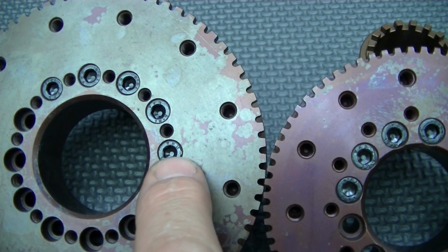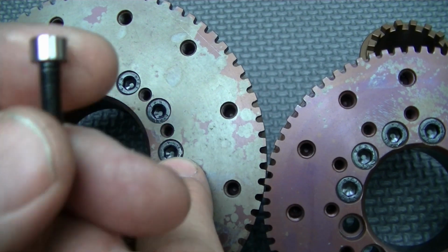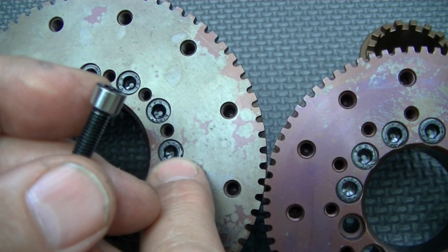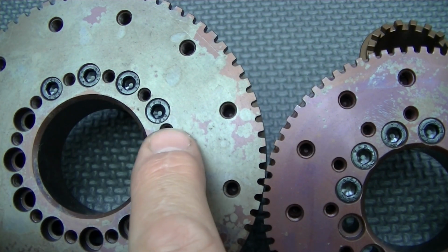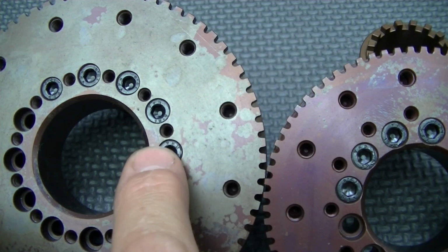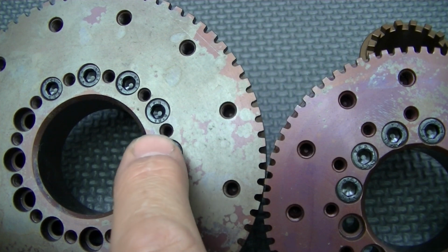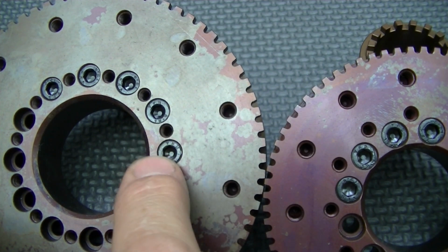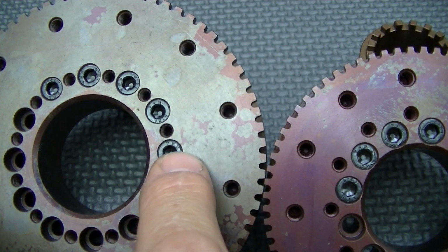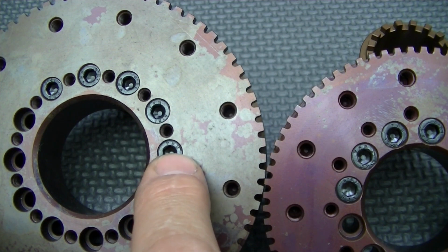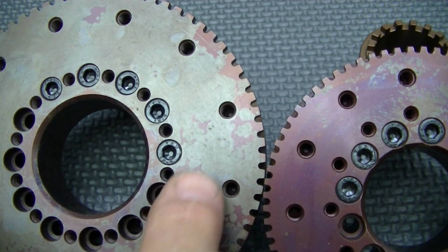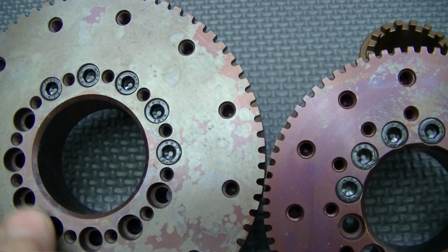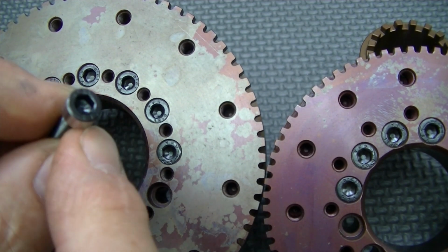It leaves these with the maximum material possible. It does not really decrease the strength of the screw at all. And it leaves a situation where this can be sealed by just using some wicking Loctite number 290 after this is installed to seal that gap so that coolant doesn't get in there, grit doesn't get in there and cause corrosion problems, and makes it easier to blow these things off when they've been covered with grit and coolant and been in service. So, important feature.